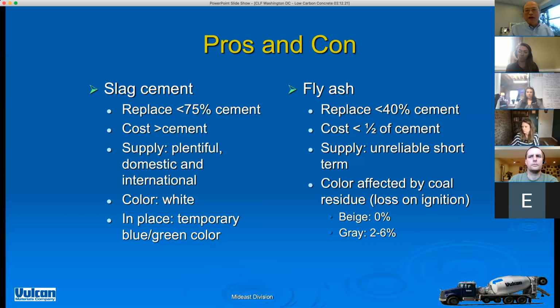I believe they're bringing that slag from Chicago, from some of the steel mills operating there. Internationally, they're telling me right now they're getting the granule from Brazil. I know that I've used slag from Italy, from Turkey, from wherever. Vulcan has also used finished slag from China a few years back. It was slag already ground in a slag mill in China that came in to Norfolk, and we were using that for a few years. One of the cement companies was importing for about 5 years. So this is to show you that it's a plentiful supply.